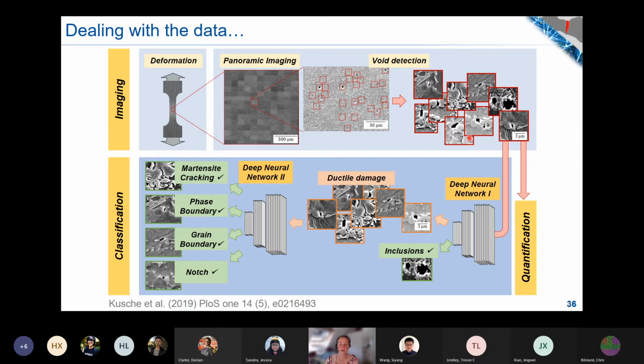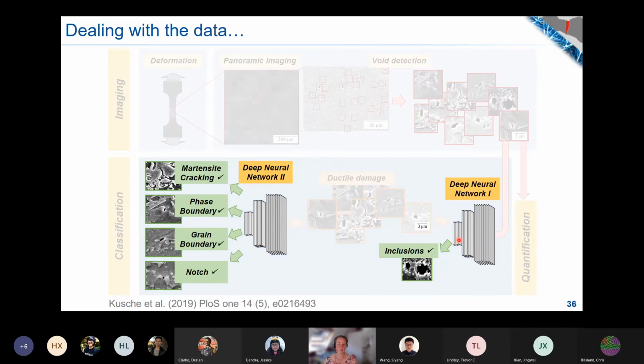But what we can also do is take all of these images and feed them through some image recognition, so deep neural networks. And there are two things we do here. The one is we wanted to separate damage that stems from the material itself, for example, inclusions that have nothing to do with the strain path, and then ductile damage, or better maybe deformation induced damage. And there are two neural networks. The one sorts out the inclusions, which are bigger and look very different, and then the second one characterizes the underlying mechanism for the images that then remain.